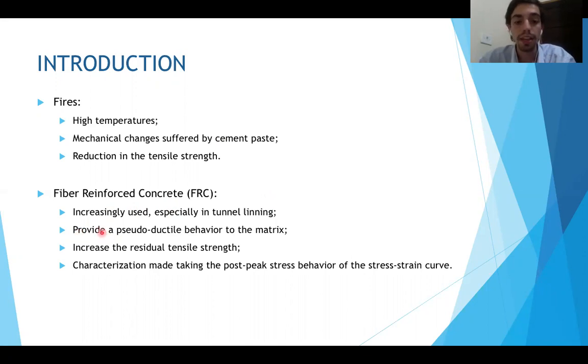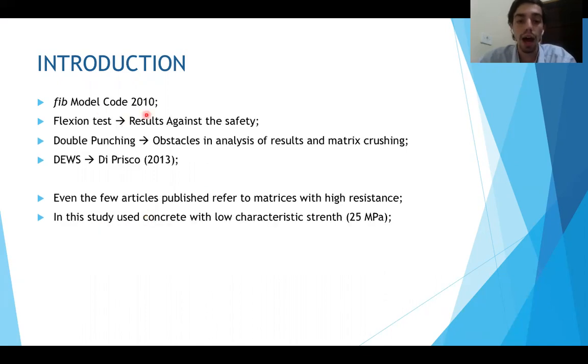The use of fibers is increasing in Brazil, especially in tunnel lining, a situation in which fire is crucial. In addition to the ductilization, fibers promote the increase of residual tensile strength, in other words, the increase of post-cracking strength. A major guide for FRC is the FIB Model Code 2010, published in 2013, which provided a great guide to the design of structures of FRC.